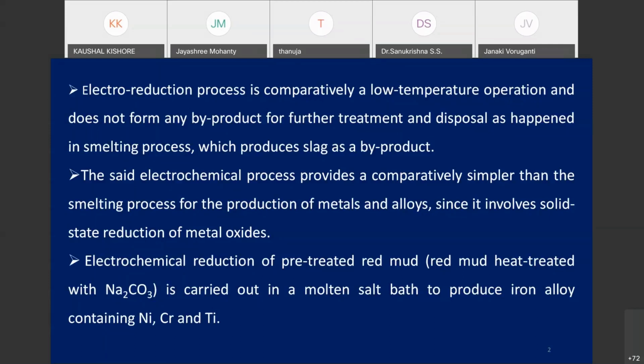So what procedure exactly we are adopting, I am saying here. First thing is that this process is electrochemical reduction of pre-treated red mud. We cannot directly take the red mud, rather it is a pre-treated red mud, that is red mud treated with sodium carbonate. So here the pre-treated red mud is processed in a molten salt bath to produce iron alloy containing nickel, chromium, and titanium. What we observe is that if you directly take the red mud for the electrolysis, it will not give you a better result. Rather, the pre-treated red mud can produce a much better result in comparison to the direct red mud material.